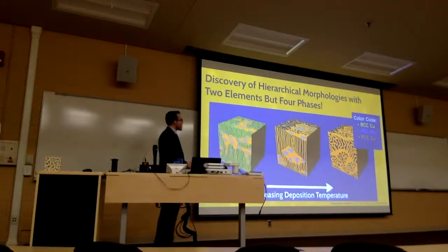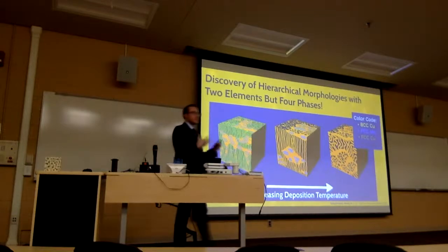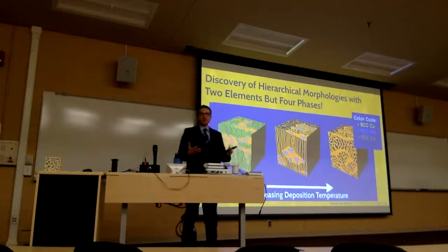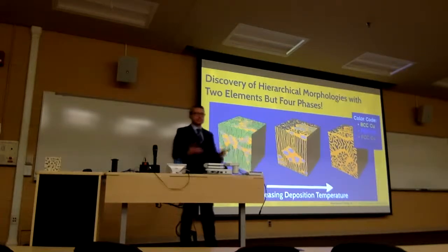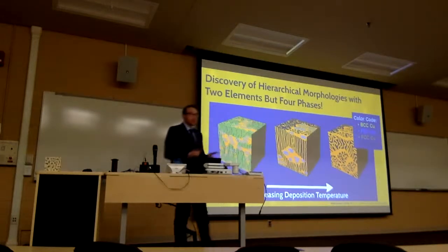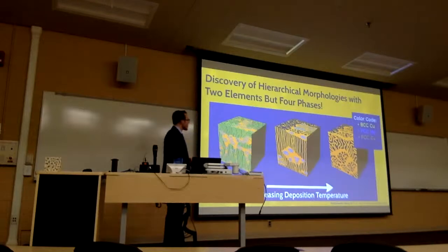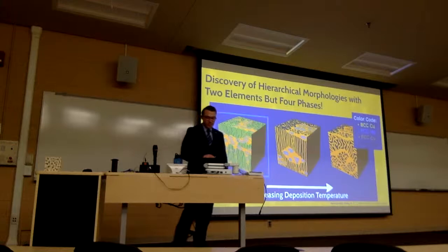And what I really want to stress is that we're only depositing 2 materials here, but what's interesting is that we have 4 different crystal structures, some of which are actually metastable or pseudomorphic. We can actually see a transition in morphology based on the deposition condition. Now, these were all deposited at low material flux, and I'd like to describe them to you today in turn.